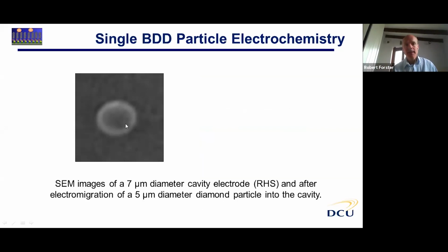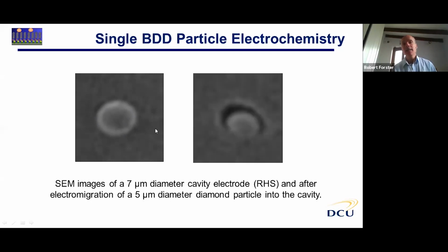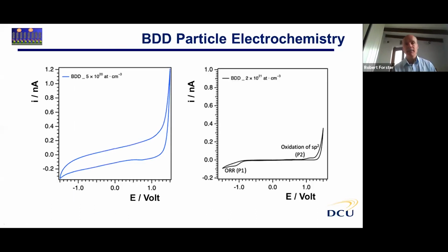So what we've been doing is taking platinum microelectrodes, for example in this case a 7 micron platinum electrode. We've been polishing those to a planar surface and then etching them back to create cavities that are roughly 7 microns in diameter and roughly 7 to 10 microns deep. The idea is that we introduce a single boron-doped diamond particle into this cavity so that we can do single boron-doped diamond particle electrochemistry in this cavity.